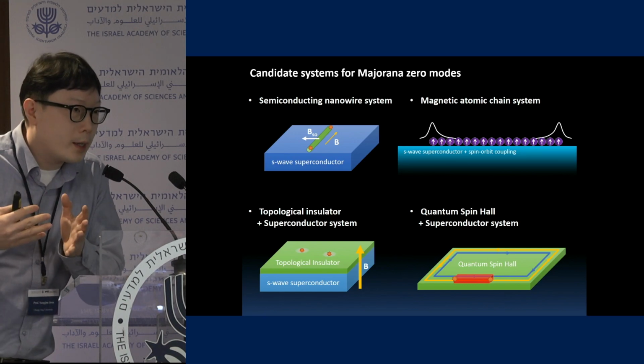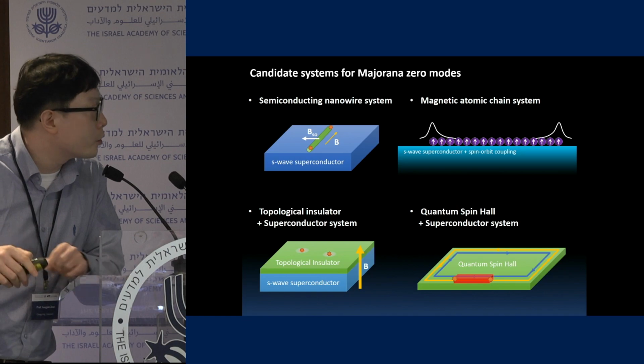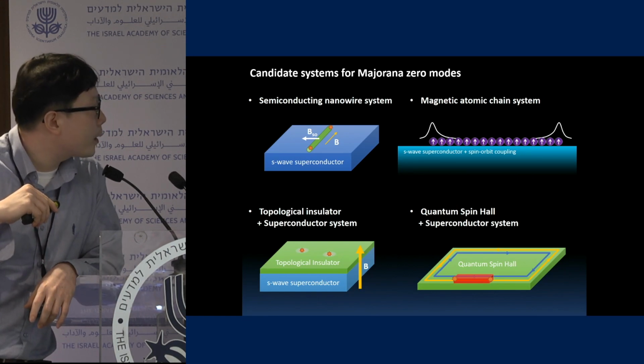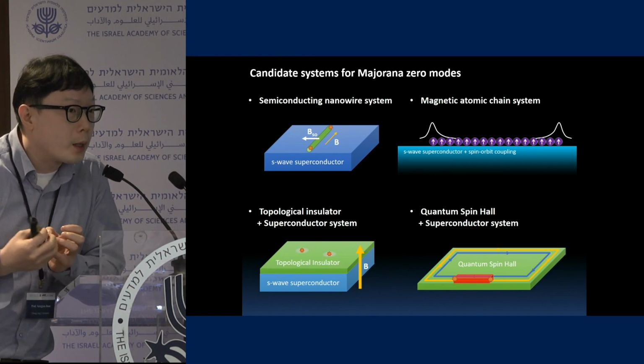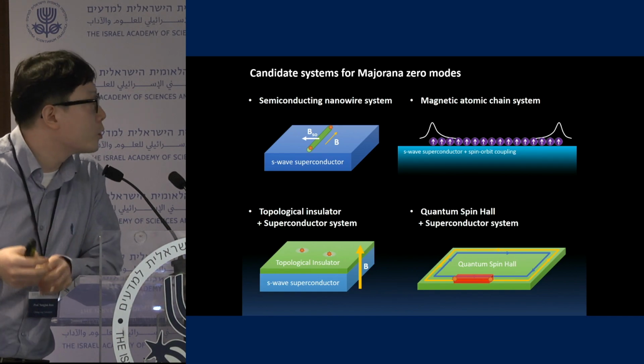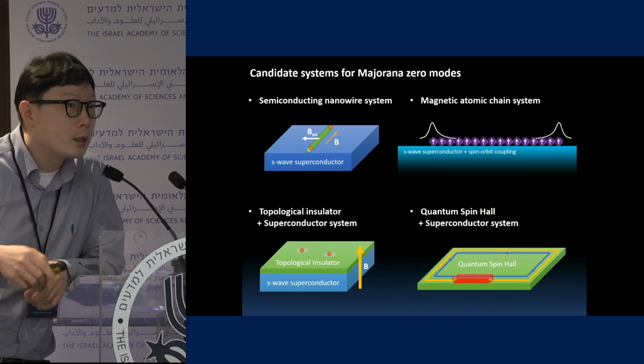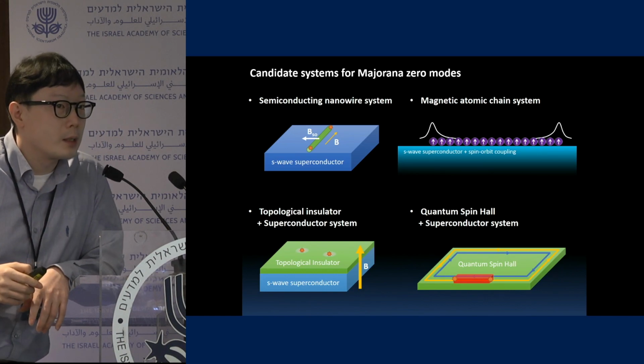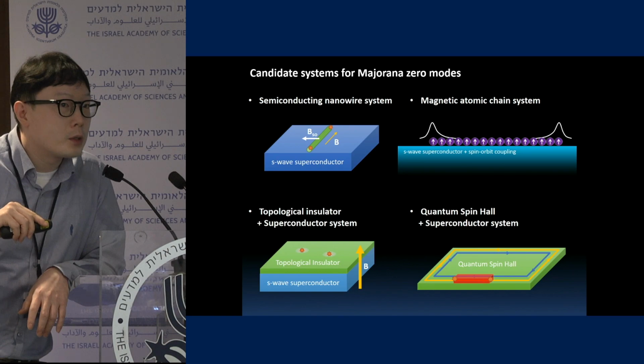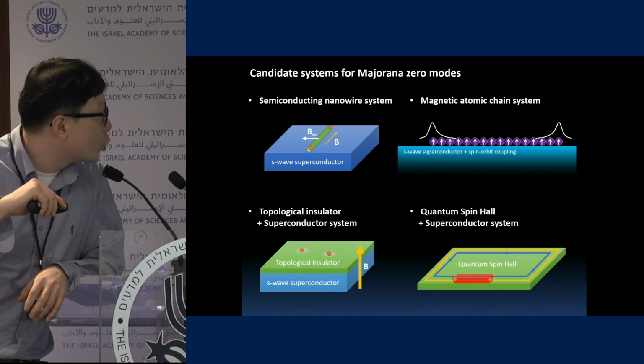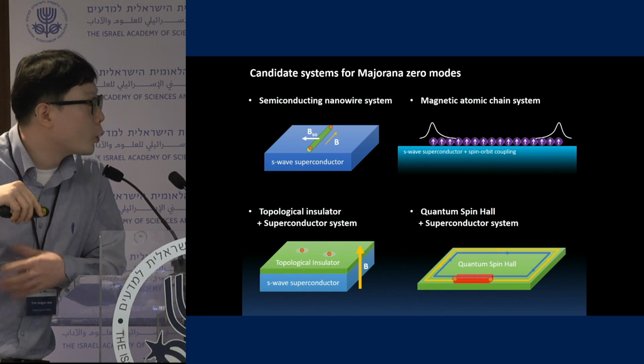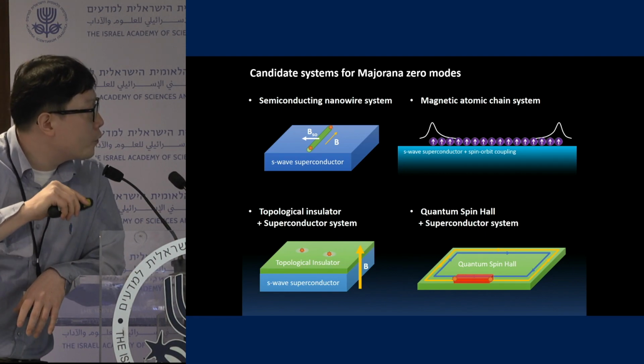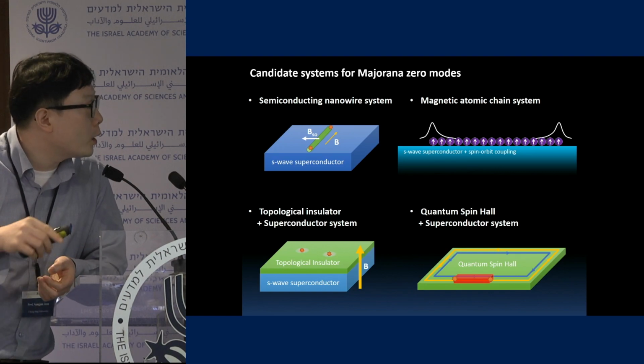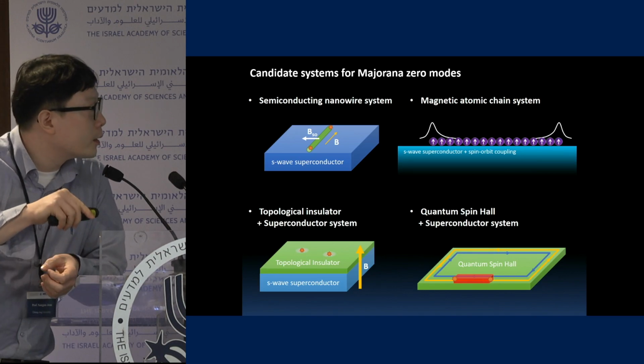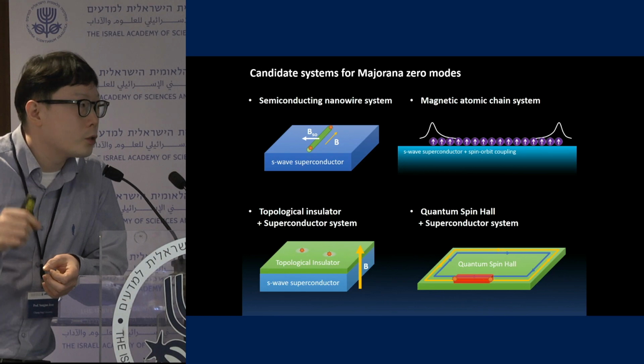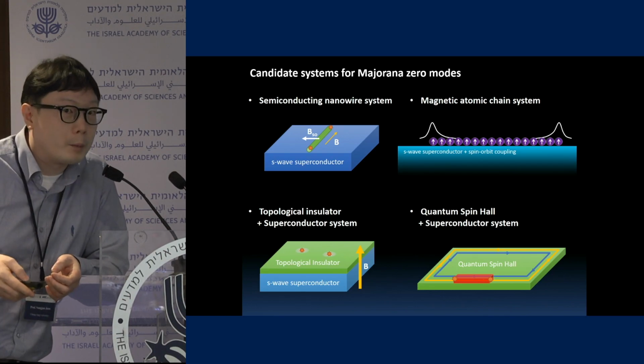So there are a couple of, actually more than several, proposals to realize this kind of Majorana zero mode. The most well-studied system is the semiconducting nanowire system, where a nanowire with strong spin-orbit coupling is closely proximitized to a superconductor, and by applying proper magnetic field and tuning, you can get a zero-energy bound state at the end of this system. The other is using magnetic atoms on a superconductor, and the other is a topological system with a superconductor, either a three-dimensional topological system or a two-dimensional version. Today I'm going to mainly focus on these two systems. Using a scanning tunneling microscope, we engineer and combine the materials to get these geometric structures and then measure the electronic structure. And that's basically what I'm going to talk about today.